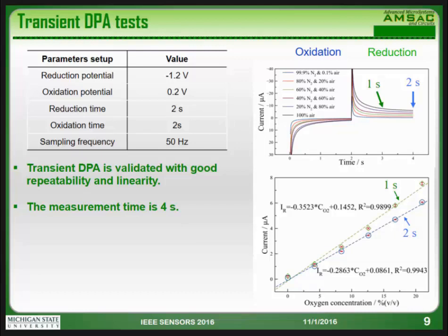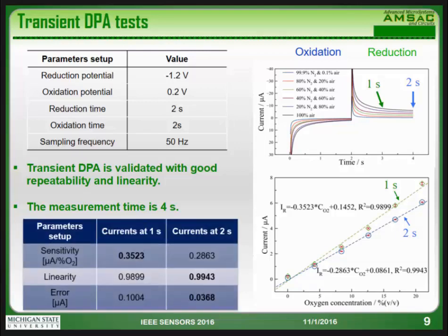So we can conclude that this transient DPA method is validated with good repeatability and linearity. And we want to emphasize that the measurement is only 4 seconds. We also made a comparison of the calibration at 1 second and 2 seconds. It shows that the sensitivity decreases with longer time, but the repeatability and the errors are improving, which means the measurement time can be further shortened if we can sacrifice some linearity, error and repeatability.